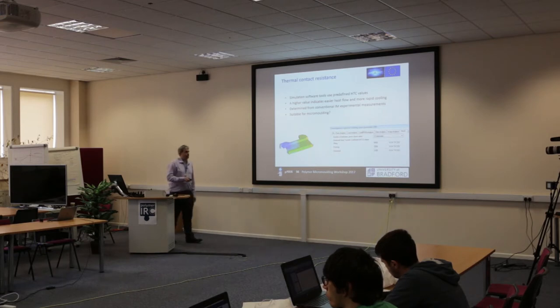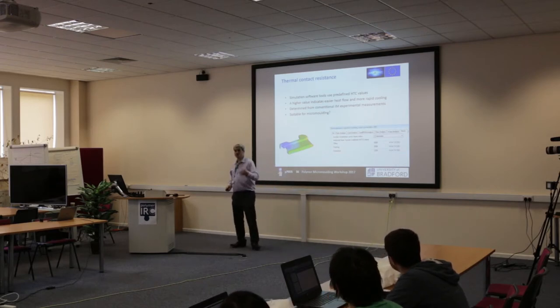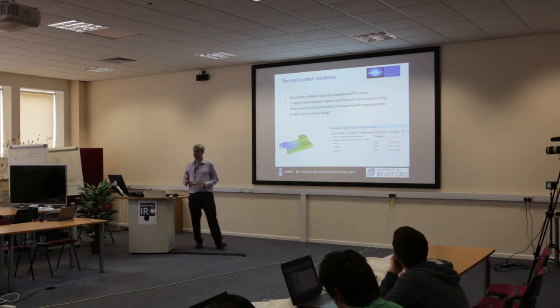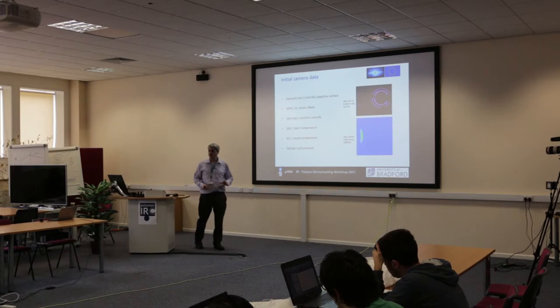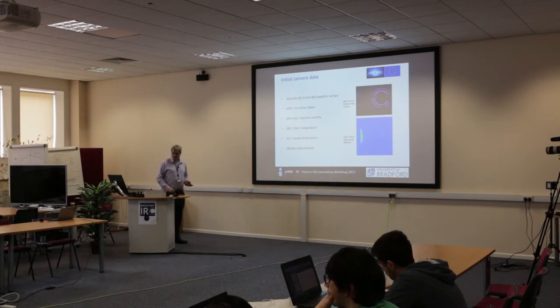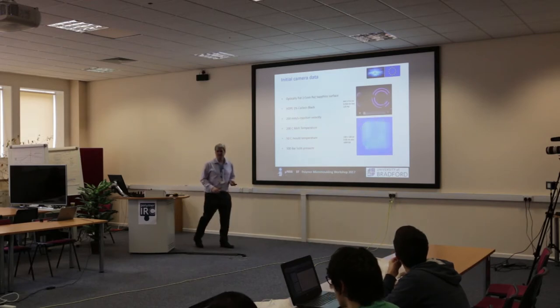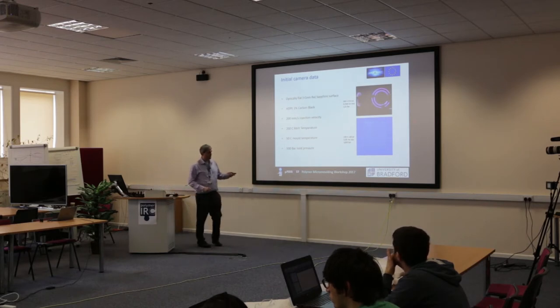Simulation software like Autodesk Moldflow uses fixed parameters to quantify the heat transfer coefficient for their molding operations, but this data was based on measurements taken back in 1999 by a research group in France. One dataset applied to all simulations — and on the whole for conventional injection molding it works pretty well — but we have to ask whether these values are suitable for micro injection molding. So we've done measurements with the thermal camera on a range of different roughness cavities and flat sapphire, using the high-speed camera as well.